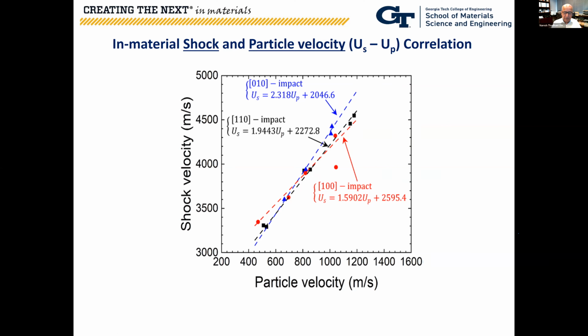Turns out that because we are considering a small sample dimension, a field of view which is 2 millimeters by 2 millimeters, within that span the anisotropy of the void orientation is very limited. Because of that, we are unable to see a clear influence of orientation associated with the impact direction relative to the print directionality for these AM manufactured materials.